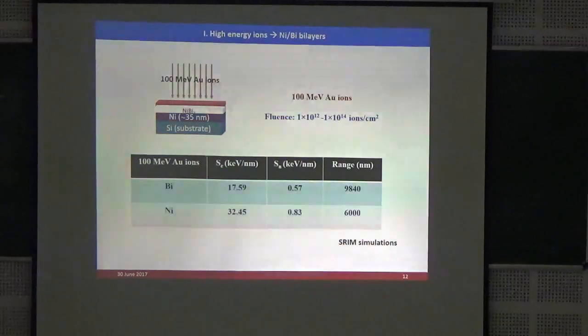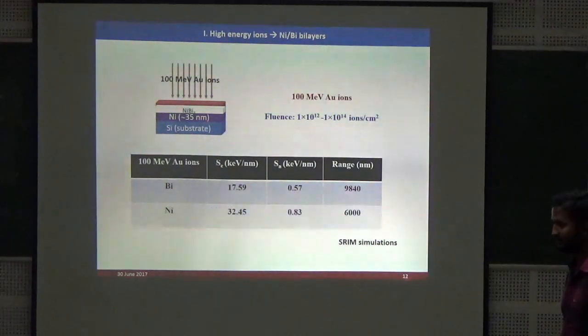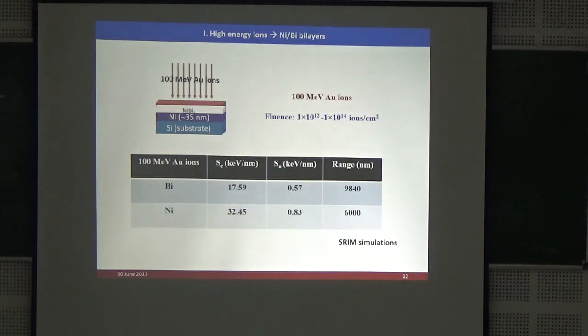In the case of high energy ions, we have used 100 MeV gold ions, as a function of ion fluence, from 1E12 to 1E14 ions per square centimeter. Using what facility? From IUAC. What is the terminal voltage of that accelerator? That is 14 MV. And what charge state did you use? 7 plus. That is the maximum terminal voltage. Right. How low can it go down?